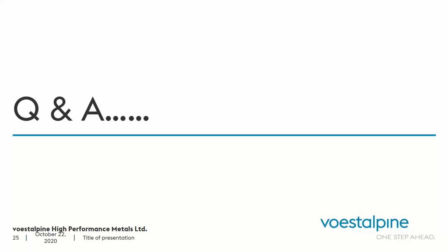Now, if you have a spot engineering change, blasting with an abrasive media at say 80, 90 psi, coating can be removed that way. It takes a little bit of time, but it will come off. You can make your machining changes or whatever you need to do, and then with polishing that area, we can recoat the whole block. We can't just coat that area. Now, best practice is to strip the coating off completely. But in a pinch, and as a cost savings measure, we have coated the entire tool again and put coating over coating and whatnot. Is it best practice? No. Is it effective? Absolutely it is. So those are your 2 options.